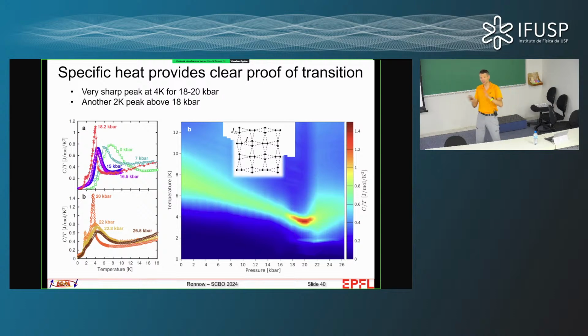So it's not directly related to the fact that we saw two excitations in the experiment, but there's this very unusual thing that it comes down, becomes super sharp, then the new peak appears, and then the main peak actually broadens out again afterwards. So spectacular data, but a little bit difficult to understand, in particular since the naive expectation would have been a soft mode transition that comes back up like this. That would have been the normal expectation for a quantum phase transition.